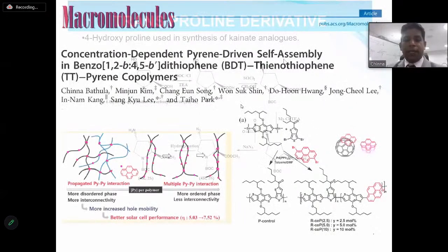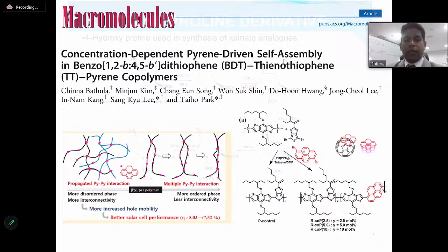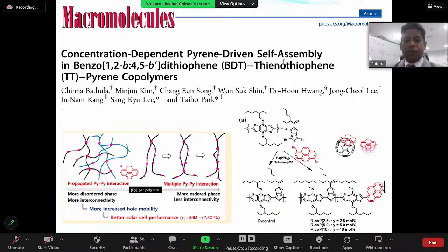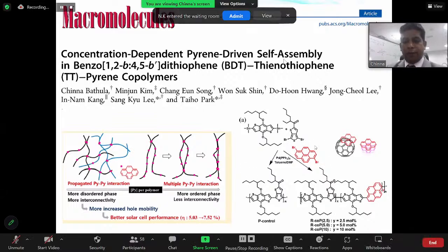And as I said, in the case of polymers, we can improve the properties by extending the pi conjugation. Here, we have done many of these kinds of polymers, but to increase the efficiency, we used a conjugated material, this pyrene, and we got promising properties. Actually, we tuned from 2.5 to 10%, and in the case of 5%, we got very good results. Here you can see all the properties shown in this slide.